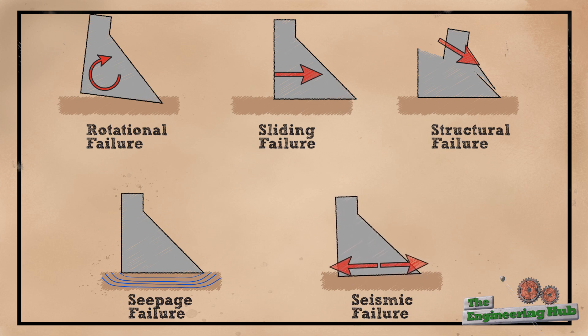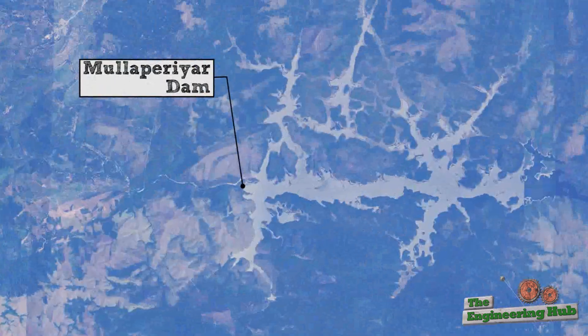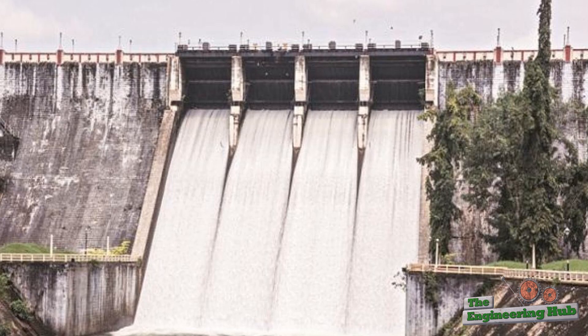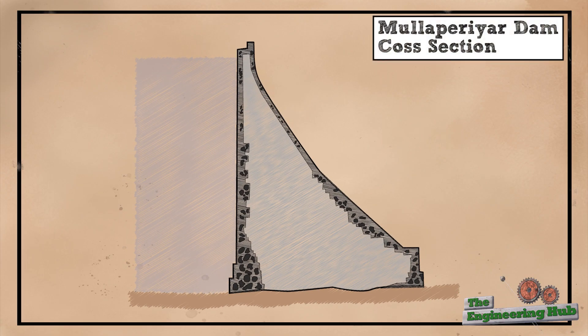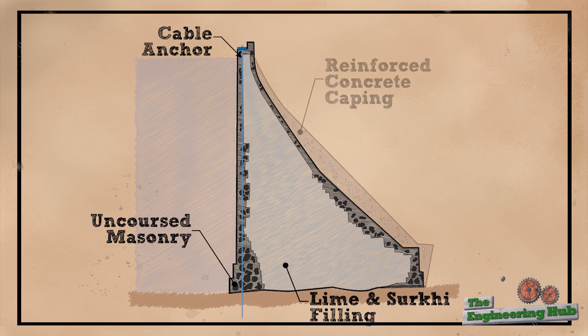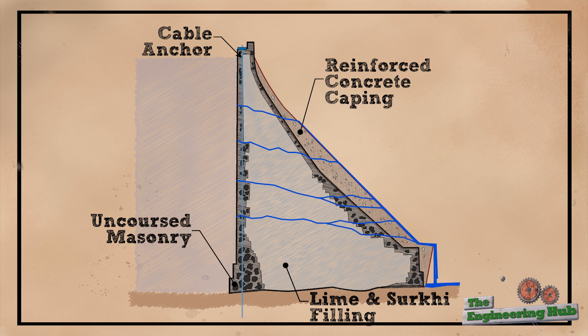One example of these concerns is the Mullaperiyar Dam in India — there is a very high chance of mispronouncing the name, so please forgive that. The dam was built more than 125 years ago, and construction materials and engineering practices have changed a lot since then. As you can see on this cross section, the dam was constructed using uncoursed rubble masonry — essentially randomly sized and randomly placed stone — and surkhi mortar, which is basically brick powder, lime, and water. During the 1980s, concrete was also added to the downstream side to strengthen the old structure, but the upstream water could not be drained to perform a full restoration. Today, the dam is experiencing seepage issues, where water under high pressure seeps through small cracks in the structure and carries out the surkhi mortar with it. Over time, this removes material and reduces strength from the core of the dam, which can lead to failure. Additionally, the dam is known to be in an earthquake-prone area without being designed as such.